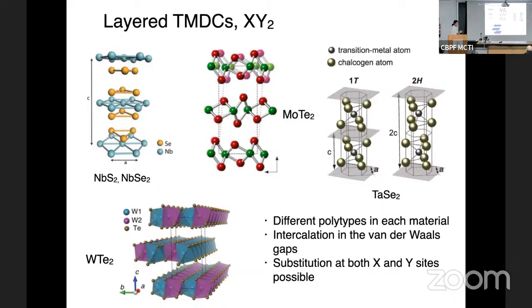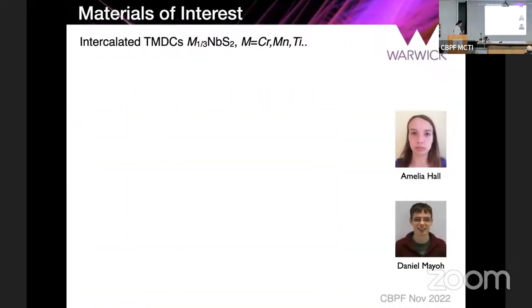Tungsten telluride has been very well studied because it's known to be a weyl semi-metal. All of them have very interesting properties in their own right. Niobium selenide is a very well-known superconductor with a Tc of 7.2 Kelvin, and they also all undergo charge density waves prior to the superconducting transition, and some of them undergo the charge density wave without really being superconducting. So they are all very interesting, and they are just a massive field on their own.